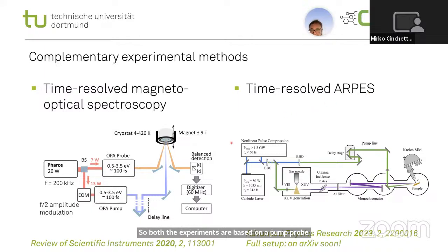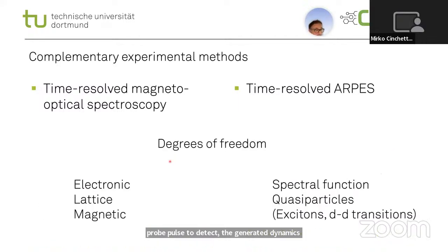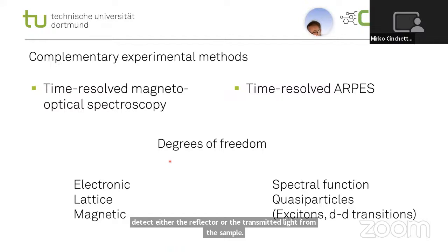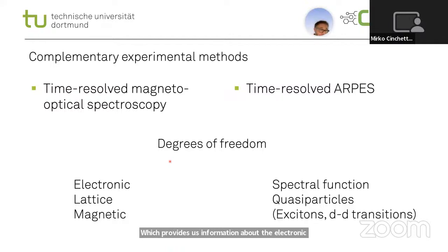So we use a pump laser pulse, which is typically tunable in the whole visible range, 0.5 to 3.5 electron volt, to excite our system to generate elementary excitations. And then we use a probe pulse to detect the generated dynamics. In the magneto-optical experiments, we detect either the reflected or the transmitted light from the sample, which provides us information about the electronic, lattice, and also magnetic degrees of freedom. While in the time-resolved ARPES experiments, we analyze the photoelectrons that are emitted from the sample by the probe pulse, and these photoelectrons give us information about the spectral function, which contains information about the electronic excitations, such as excitons.